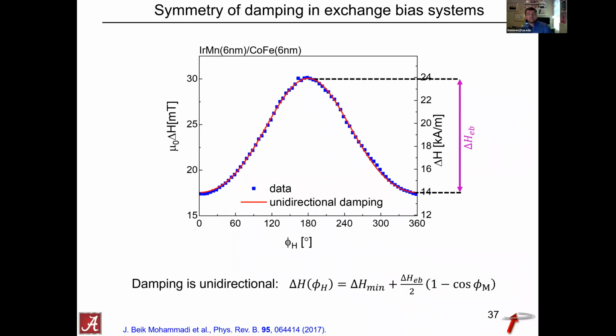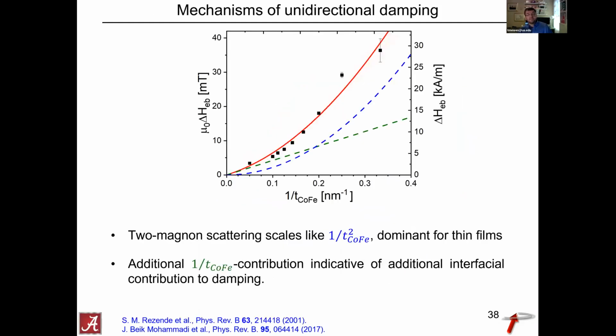And you can do this as a function of the film thickness that you investigate. So this is a whole series of films here. And what you see here is the data points in black. And you cannot fit this data set with a simple fit. So it's just a 1 over thickness squared dependence. That fit does not work.